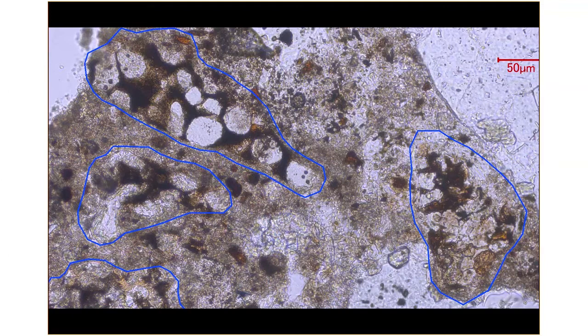That's the whole process of Portland cement: calcium silicates and water. And we control the set by adding gypsum to the mixture, which forms ettringite very early on. And Bernard mentioned ettringite very early on. Ettringite is a very important part of Portland cement hydration, and helps with controlling set, and keeps these calcium silicate crystals from flash setting and getting that concrete to set even in your mixer. So we add sulfate to combat that and allow the sulfate to break down over 3-4 hours and allow the concrete to set.